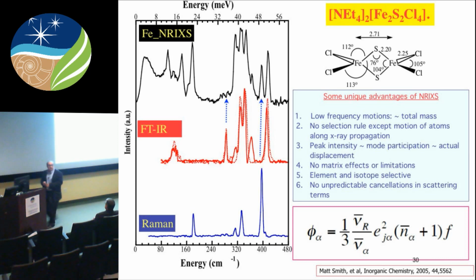In terms of forward scattering, if you put half micron iron, it's 10 minutes, you have good data. And we are developing a method that will reduce that to a few seconds, actually, maybe at the end of this year. And does sample size help? We typically have about a 10 micron, 15 micron beam. So if you have a 20, 25 micron sample, that's enough. So we're talking about nanograms. It can be a glass, it can be single crystal, it can be powder, we don't care.